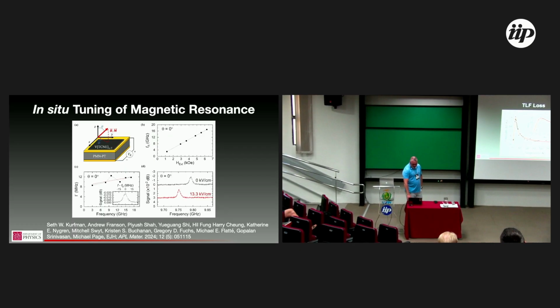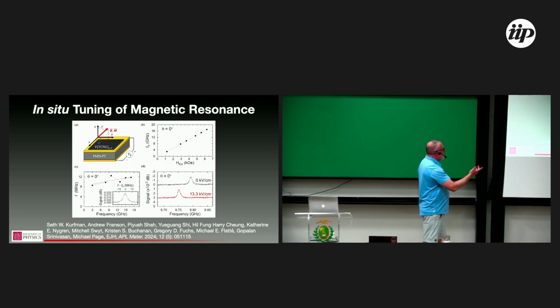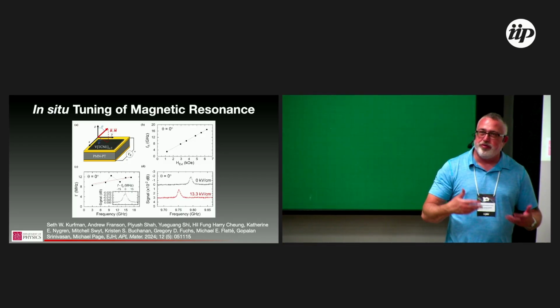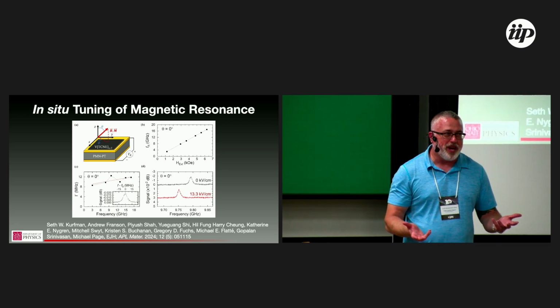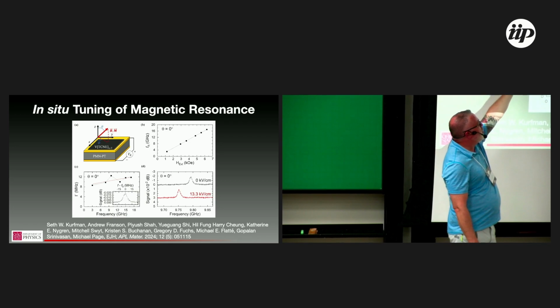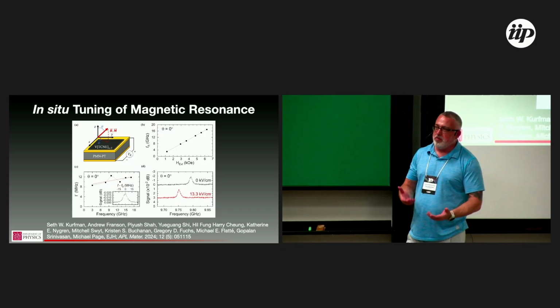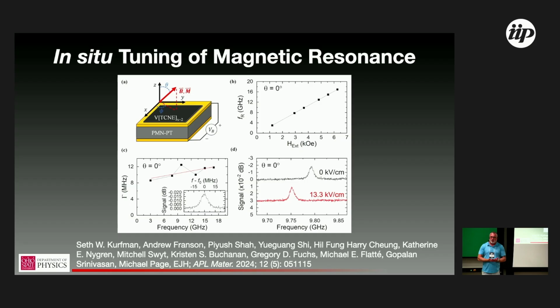Okay, so with that reframing, what we did next, which is what conceptually you would do first if you want to explore strain, is we built a system where we just bonded a V[TCNE]x film to a piezoelectric wafer, where we can control the strain in ways that are controlled and understood, rather than relying on some self-assembled structure that builds itself with intrinsic strain, in the nanowire example, or in the temperature dependence, where we're using temperature and the difference in coefficient of thermal expansion to put in the strain. We'll just use strain to put in the strain.